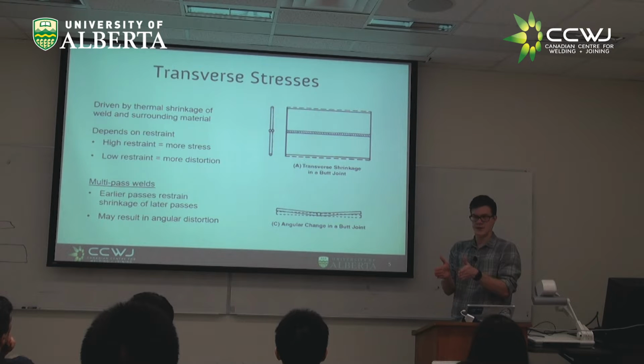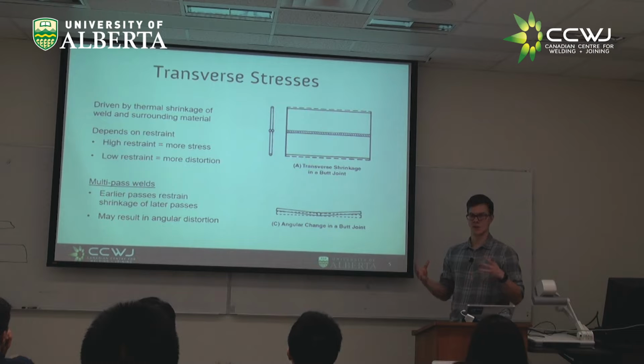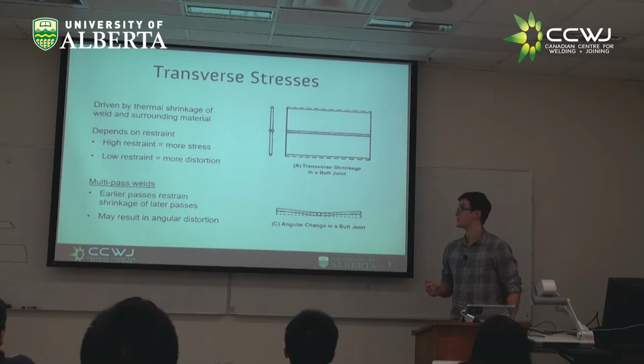And that actually closes up the gap and compresses that metal while it's very hot in the weld and doesn't have a capacity to handle that stress. And then it locks itself in that closed position. And as it shrinks, it's now pulling back to return to its original shape. So it's not just the weld metal that's shrinking because you had molten metal, it's the surrounding material that got heated up to the point that it expanded into that gap, and now it's returning to its original shape. So transverse stresses depend highly on the restraint.